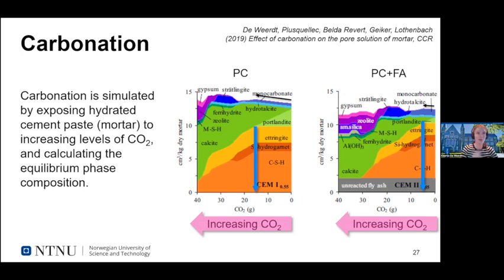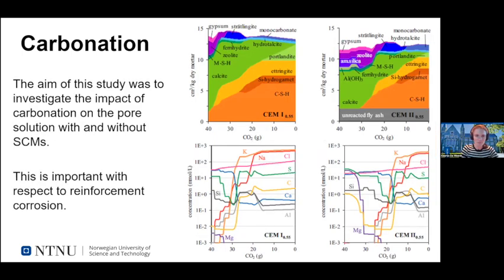But we were interested in the pore solution. The graphs on the bottom show the pore solution as a function of the CO2 added to the system, which is in equilibrium with the solid compositions above. We really wanted to know how these SCMs affect the pore solution in the carbonated state. That's important because when the concrete or the mortar has carbonated, that's where corrosion is going to take place. So what is actually the environment of the rebar in this carbonated mortar or concrete?